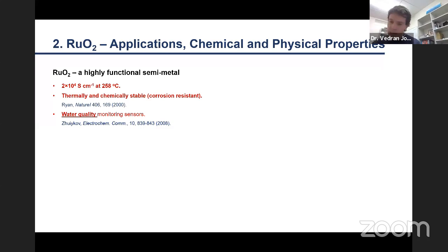However, in terms of functionality, it's one of the most functional materials, and it owes its functionality to its electronic and ionic conduction properties and favorable thermal and chemical stability. It's in some instances corrosion resistant, and its diffusion properties are beneficial for various sensing applications. It also has particularly high Coulombic efficiencies, its ability to facilitate an electrochemical reaction, and it has very good mass transport properties. So this material is actually a prototype conversion material for metal oxide lithium-ion battery electrodes, with high charge storage capacity, supercapacitors, and all of these kinds of neat applications.